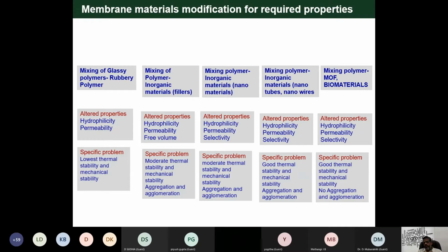But we did some consultancy with a small industry, where we coated ceramic with polymer materials. The coating is stable for only a few days or a very short time, not for a long time. To avoid that, you distribute a modifier into any kind of polymer material, then you can alter or modify the material. In the 90s, people worked on glassy polymers and rubbery polymers mixed together to make the membrane. The hydrophobic, hydrophilic property is altered.